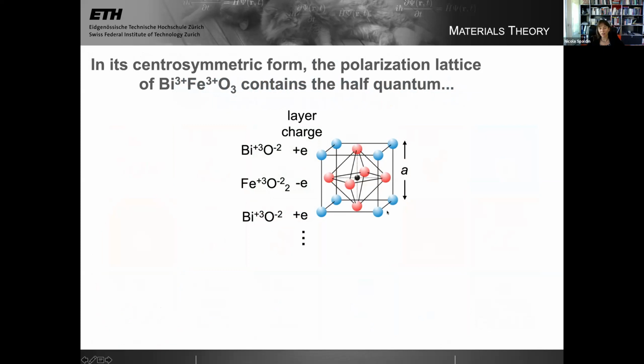Here's the perovskite structure, bismuth ferrite, in its ideal cubic structure with no polarization. So the positive ion is right in the middle of the negative oxygens. The bismuths are exactly at the corners in a square, and so there's no dipole. If we look at the charges of each layer, this layer in the unit cell has 1 bismuth and 1 oxygen. It's bismuth 3 plus, oxygen 2 minus, so it has a charge of plus the electronic charge. The next layer has 1 iron and 2 oxygen ions. The iron ion is plus 3, each oxygen is minus 2. So the charge in this layer is minus 1 electronic charge, and so on.